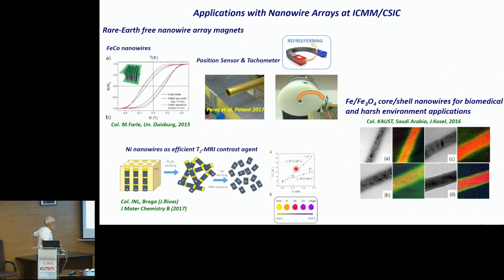Also, in collaboration with Jürgen Kosel, now he's back in Austria, they prepared core shell iron magnetite nanowires. You see here, this is a function of some thermal treatment they did. Because the external magnetite shell protects the material, the nanowires, and the internal iron core increases the magnetic signal.